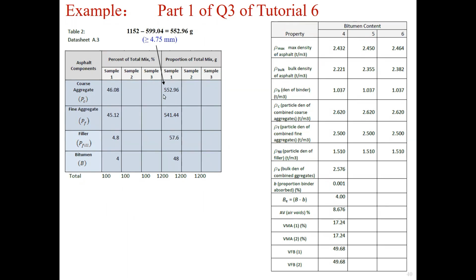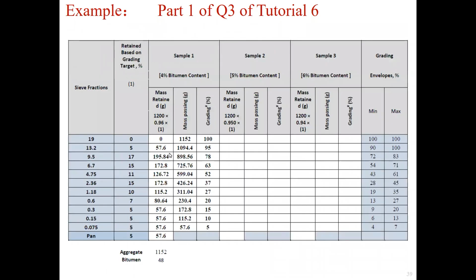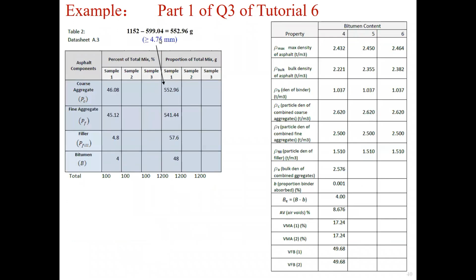If we take PC for example, it corresponds to the retained weight for sieve size equal or greater than 4.75 millimeters. So if we go back to the previous slide, the total weight of aggregate is 1,152 grams, and the mass passing the 4.75 millimeter sieve is 599.04 grams.